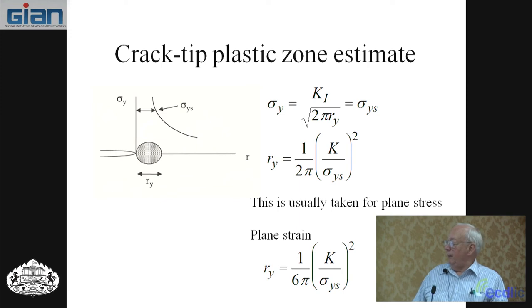It's usually called the plane stress plastic zone. If you have plane strain, which we'll talk more about later, but means more of a thickness constraint, a very thick structure, the plastic zone can be smaller and can have a 1 over 6 pi. So you go from 1 over 2 pi to 1 over 6 pi. And the reason we picked 1 over 6 pi is because one time George Irwin said, I think you ought to use 1 over 6 pi for plane strain. And everybody said, yeah, we ought to use 1 over 6 pi. So ever after that, we've used 1 over 6 pi. However, when in doubt, use 1 over 2 pi.